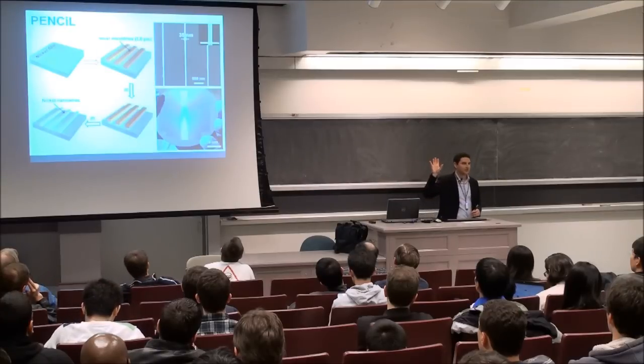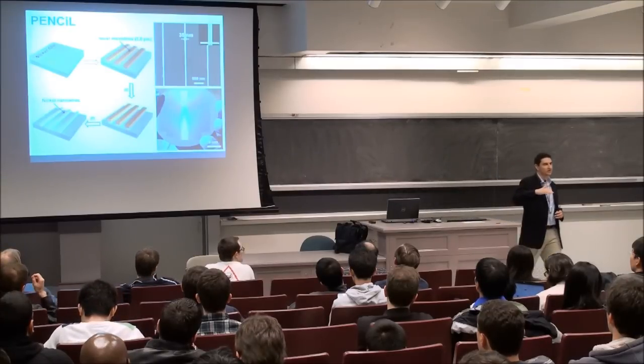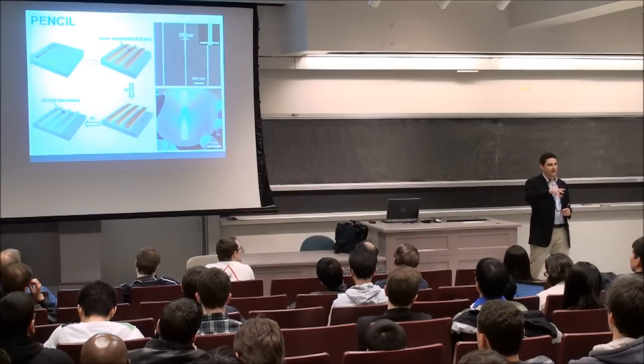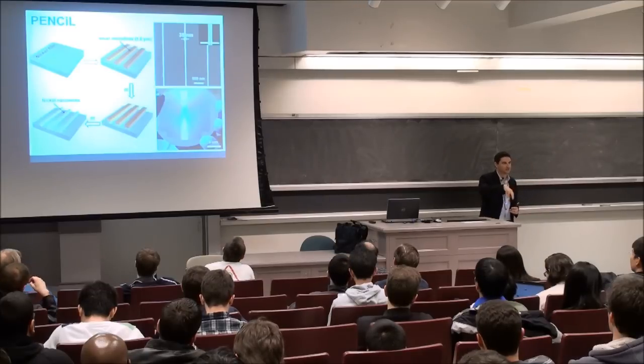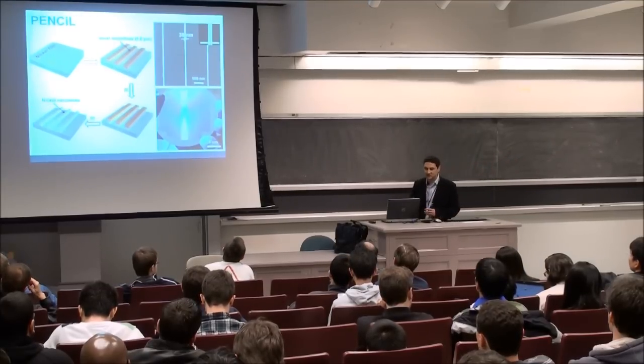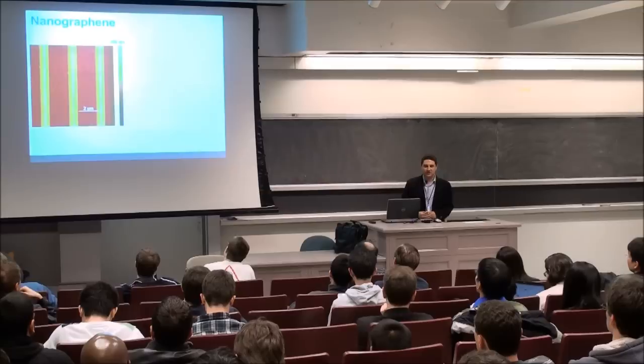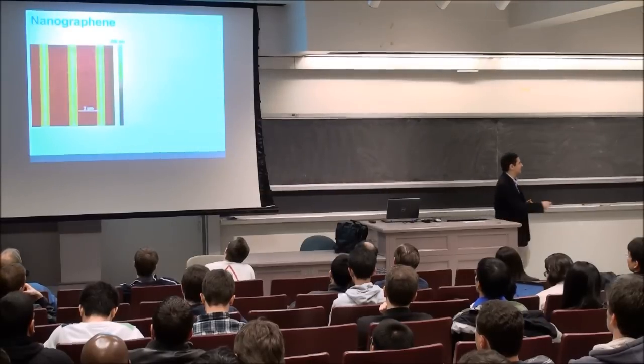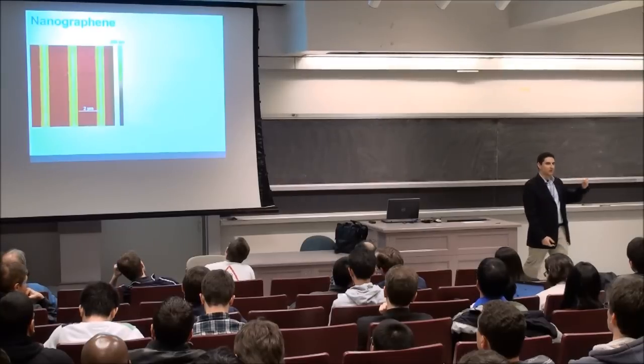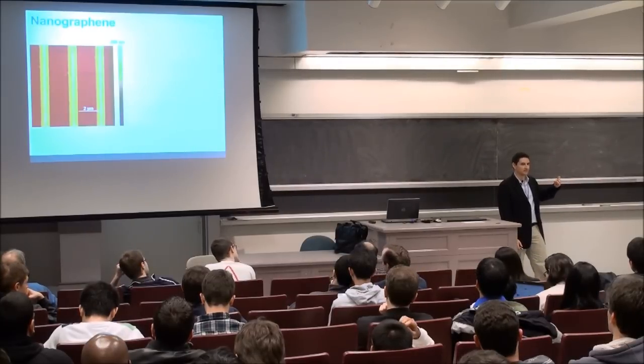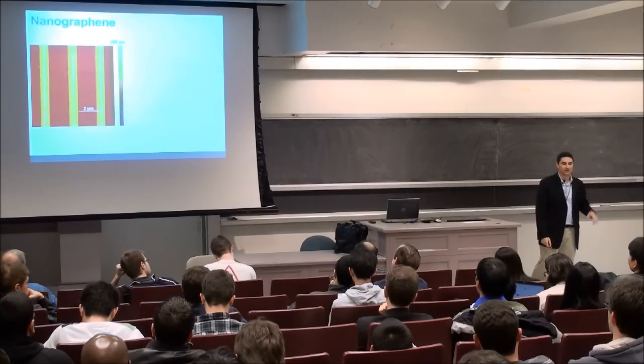So the point here is that if you have graphene underneath that nickel layer in the first place, you can then translate those nickel nanowires into the graphene underneath and form nanoscale graphene. So this is what it looks like here with the nickel patterned here, and underneath each of these nickel nanowires is actually a nanoscale graphene. Okay, and the background is a silicon wafer.